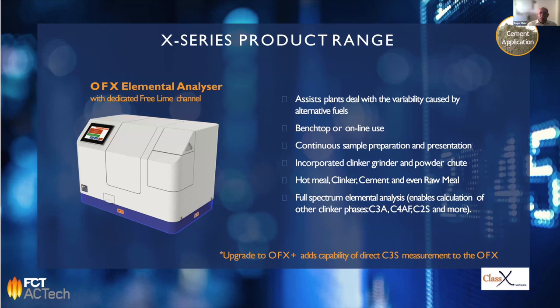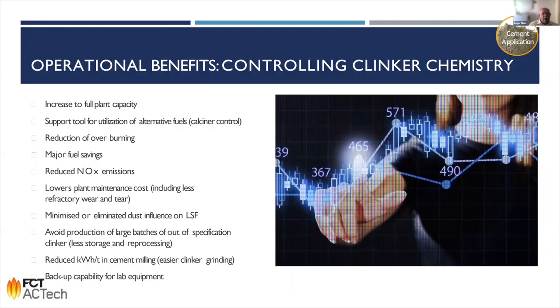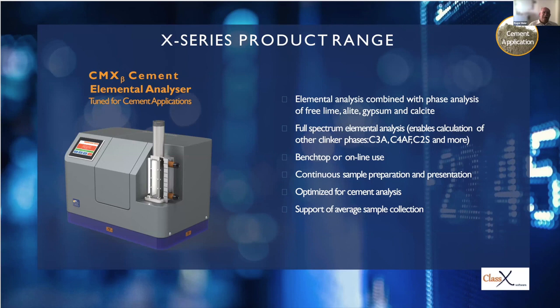If you go later more down in the process, or also at that point, you can use the OFX, which is a mixed analyzer. It has 2 X-ray tubes and 2 detection systems to be able to measure the mineralogy and the chemistry. And this gives you the full picture of the composition of the materials, and you can really tune the process in a way that it's super efficient, but that it's also sharp at the target values, not to waste energy. But you guarantee at the same time that you are on spot and your customers get the materials they expect.